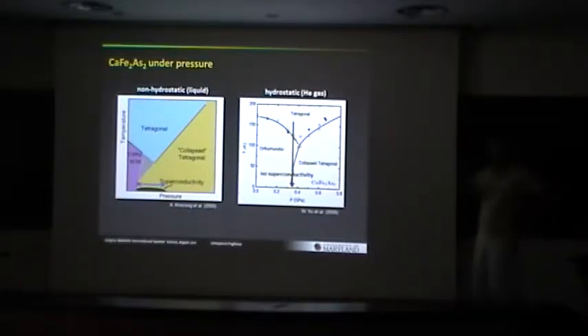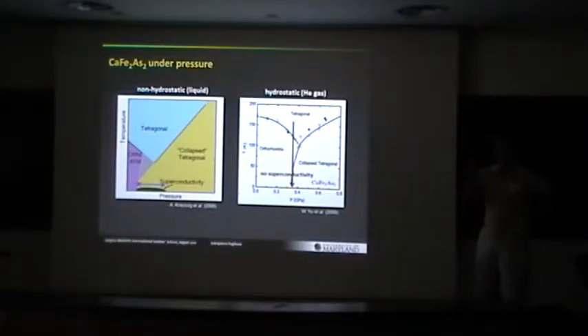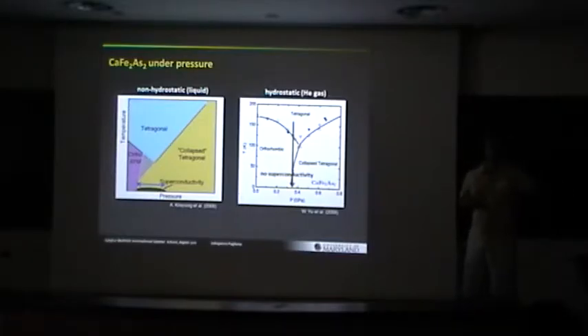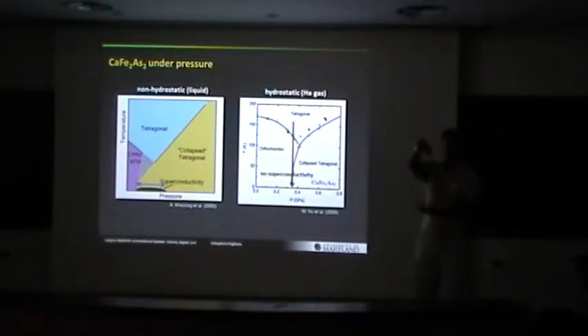One of the consequences of measuring a sample that undergoes a 10% change along one direction under pressure is that when you do this measurement in a pressure medium that's not helium, you end up with some very strong straining on the crystal. So you imagine that you have some liquid pressure medium that becomes a solid at low temperature, and you have a sample in there, and you're cooling the pressure cell down, and then suddenly this sample shrinks by 10%, well, you have a void in there and you have a very strong anisotropic strain on the crystal.